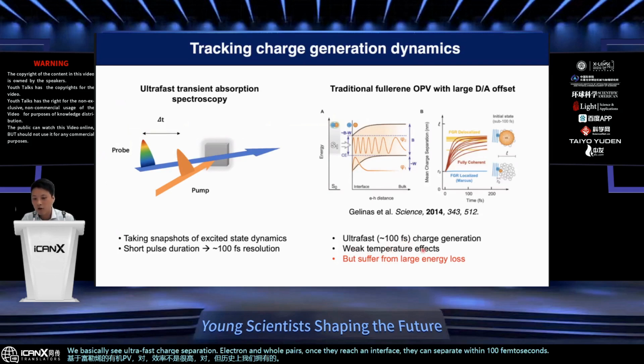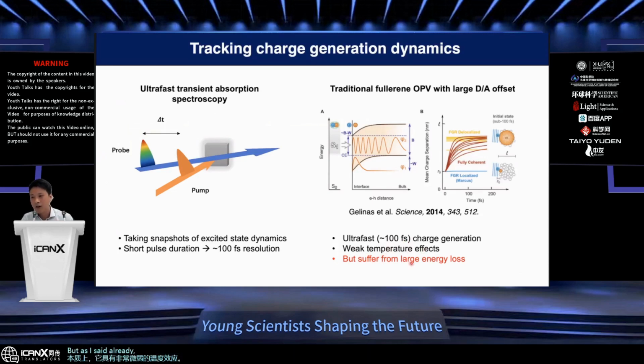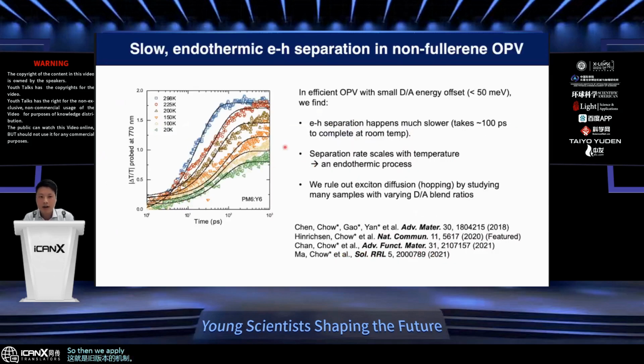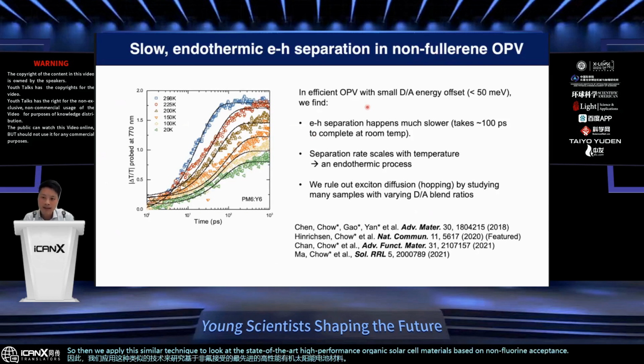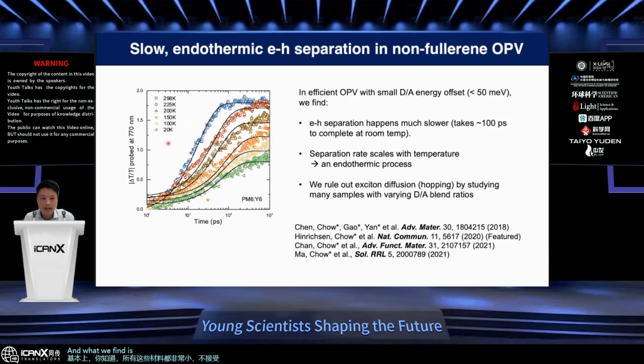And essentially, there are very weak temperature effects. But as I said already, because you engineer this large energy offset at the interface, you also end up losing a lot of energy during this charge separation process. So this is the mechanism of the old version. Then we apply this similar technique to look at the state-of-the-art high performance organic solar cell materials based on non-fullerene acceptors. All of these materials have very small donor acceptor energy offsets. What we find, if we track the electron hole separation as a function of time, is that first of all, the electron hole separation process happens at a much slower time scale.